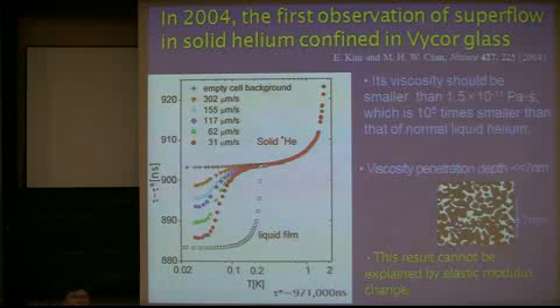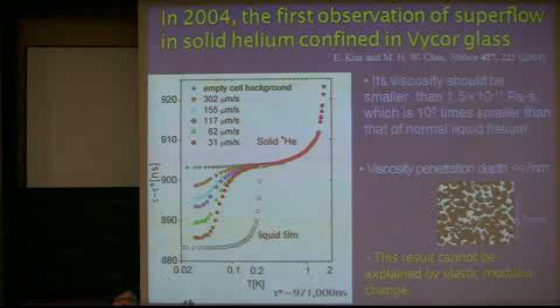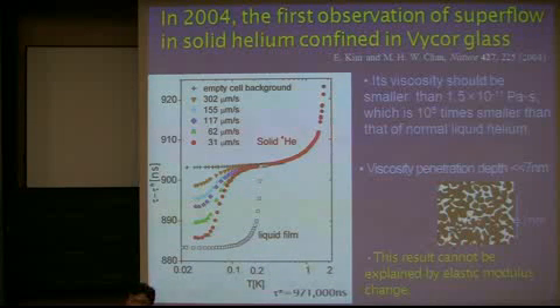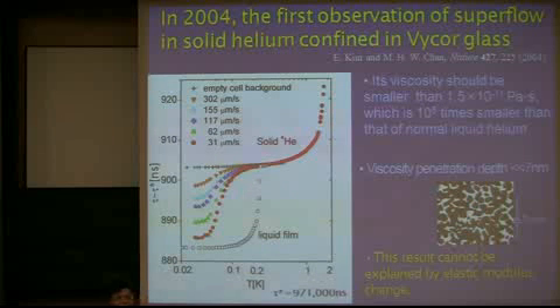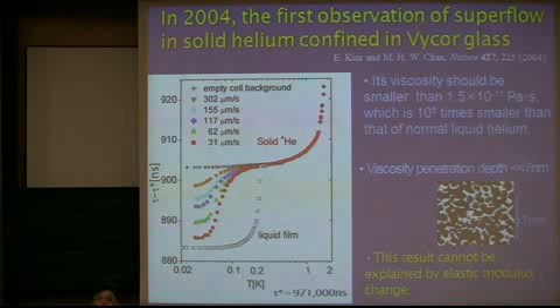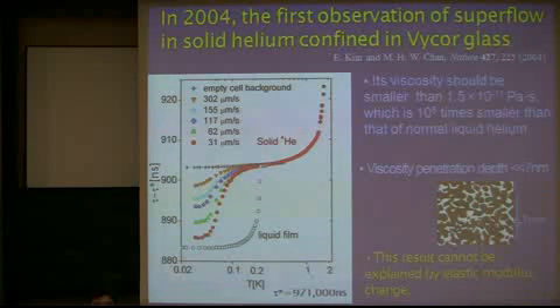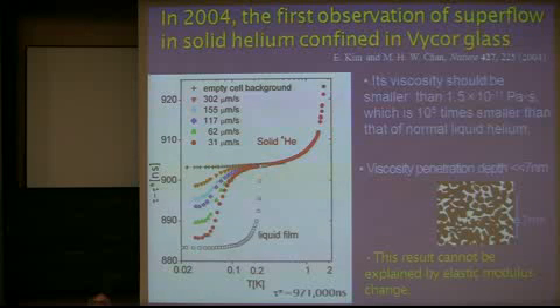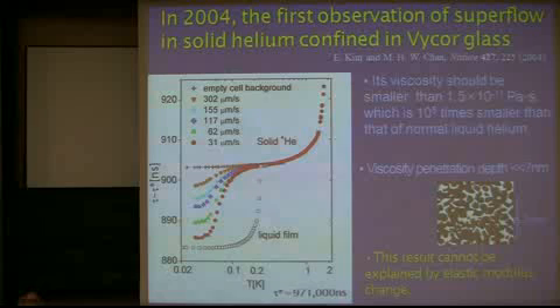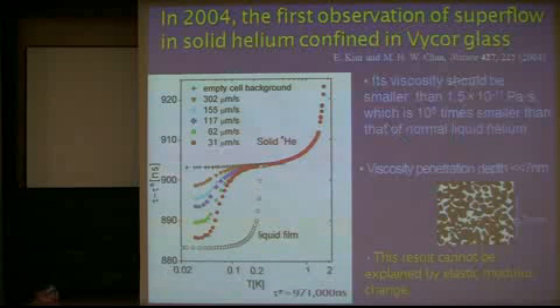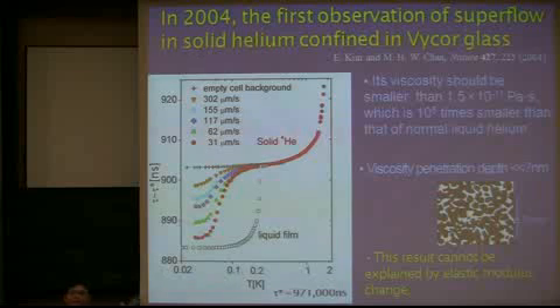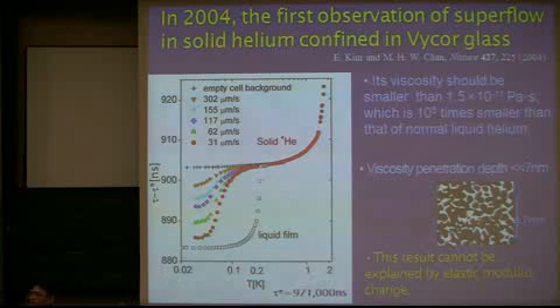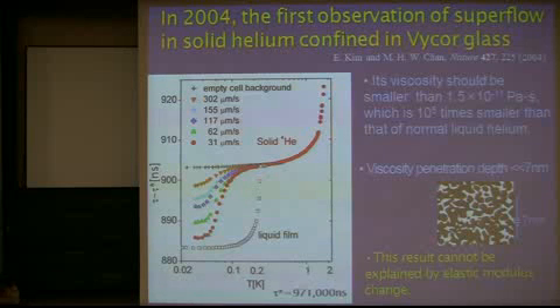One thing I want to emphasize here is that we use the 7 nanometer pore Vycor glass, so solid helium is confined in the Vycor glass, 7 nanometer. If you think about the motion of any kind of liquid or solid, it is strongly suppressed. There is no motion because of the 7 nanometer size. So if there is a motion or flow, there must be superflow. You can simply calculate that using the viscosity penetration depth idea. Okay? Good.